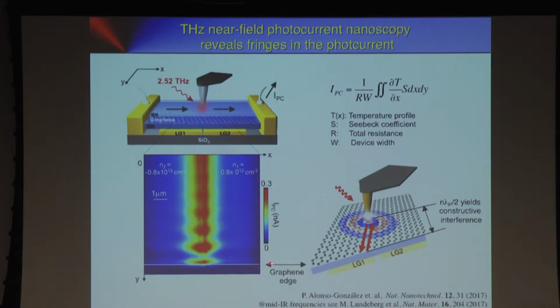But then if we scan close to the edge, we have seen these modulations in the photocurrent. And this we could identify as terahertz plasmons in the graphene sheet that propagate in the device. Now the graphene is the material that supports the plasmon. This is the one that we want to see, but we use the graphene itself as a detector. And that's a very nice possibility to avoid the use of far-field detectors and increase the signal to noise.